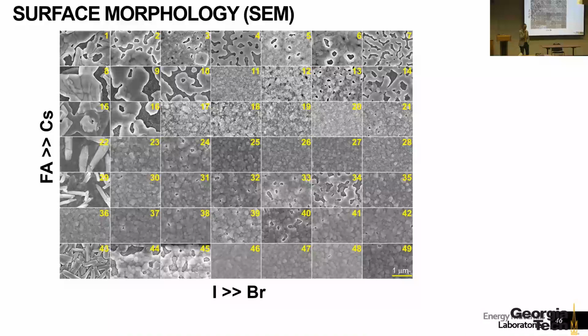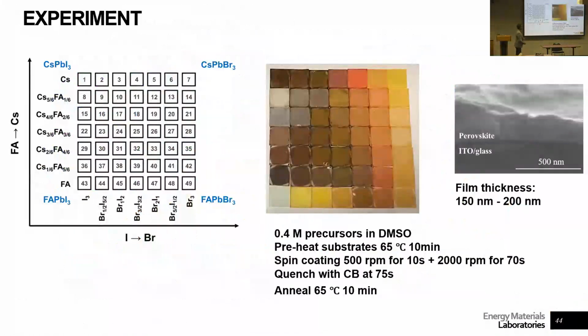Given the current status of stability, you showed different options for halides, different options for cations, like cesium or what have you. What is the current feeling about which of these elements give you more stability, or is it not very clear? I think there is, and we've been exploring this a lot, and it's going to be right around here. A mixture of formamidinium, which is a very large cation with 2 nitrogens, and the cesium. With the pure cesium and the pure formamidinium, you can already see that this is already degraded. This is white. The pure formamidinium is very unstable. The pure cesium, here you cannot see, but this one is clear. It also becomes white very quickly.